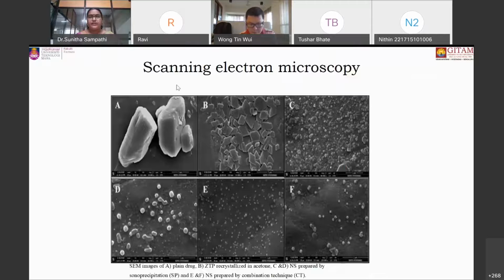Later, we subjected that to scanning electron microscopy. And if you look at the images of the drug, this is the pure drug, as well as the drug which was precipitated from the organic solvent. They are rectangular blocks and the size was more than 5 microns. The nanosuspension prepared with the sonoprecipitation technique is reported in C and D.